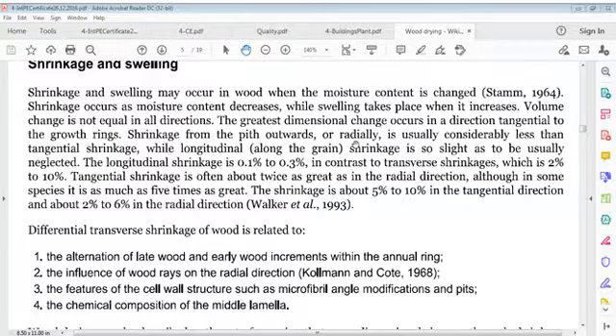Volume change is not equal in all directions. The greatest dimensional change occurs in a direction tangential to the growth ring. Shrinkage from the pith outward, or radially, is usually considerably less than tangential shrinkage, while longitudinal, along-grain shrinkage is so slight as to be usually neglected. Longitudinal shrinkage is 0.1% to 0.3% in contrast to transverse shrinkage, which is 2% to 10%. Tangential shrinkage is often about twice as great as in the radial direction, although in some species it is as much as 5 times as great. Shrinkage is about 5 to 10% in the tangential direction and about 2 to 6% in the radial direction.